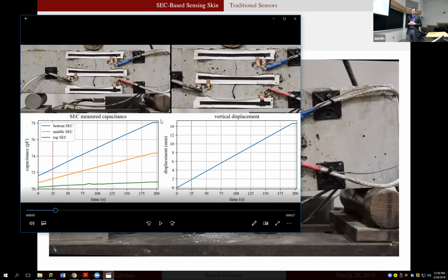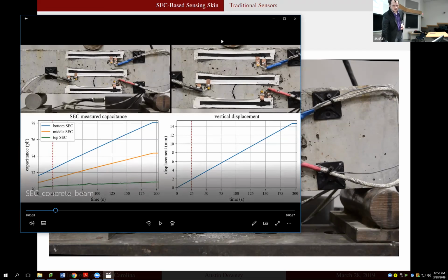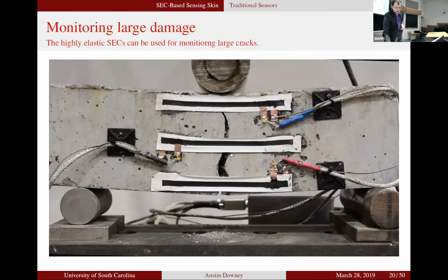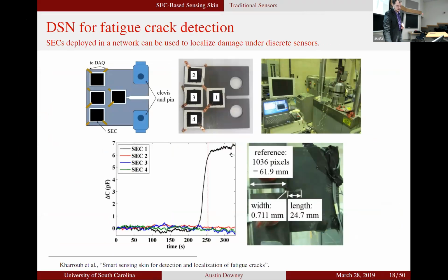But do you know what is the minimum crack size that can be detected? So we're doing fatigue cracks, right? The minimum crack size is not actually a function of the sensor, it's a function of the SEC itself. I would have to get with the team from Kansas to get you a number, but it's fatigue crack size. We're not having any issue detecting fatigue cracks. Those are glued completely, the fatigue crack ones are.